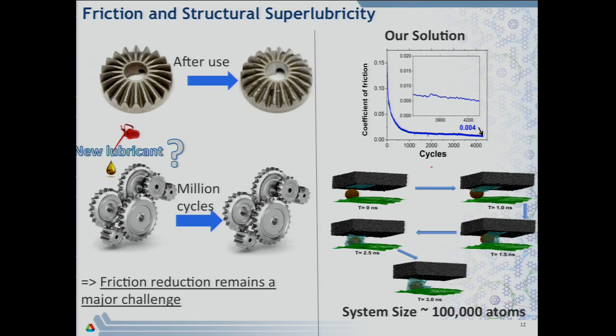The choice of nanodiamond was practical — the force field we used in the simulations didn't need to change if we used a carbon-based material. We showed that graphene could scroll over nanodiamonds and remain stable, since the nanodiamond was sandwiched inside the scrolls and would never let the scroll collapse. When we calculated the friction coefficient between these interfaces, it was always in the 0.004 range. When tried in experiment, indeed there was very smooth variation down to 0.004 — structural superlubricity.